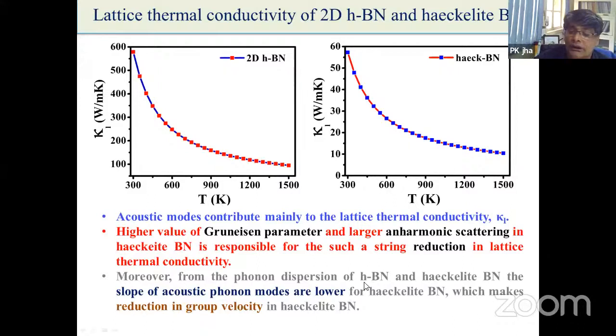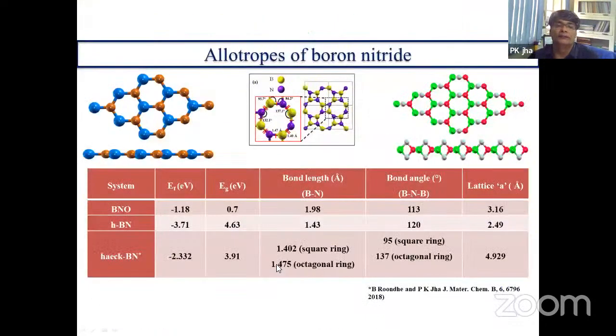From the phonon dispersion curve of hexagonal boron nitride and haeckelite boron nitride, we can see the slope of acoustic phonon modes is lower for haeckelite boron nitride, which makes a reduction in the group velocity in haeckelite. That means what? That the group velocity should be lower, right? That means if the slope of the phonon dispersion curve is lower, that will lead to the reduction in the group velocity, and if it reduces the group velocity, naturally you will have the lower thermal conductivity. So that is the point you can basically see, right?